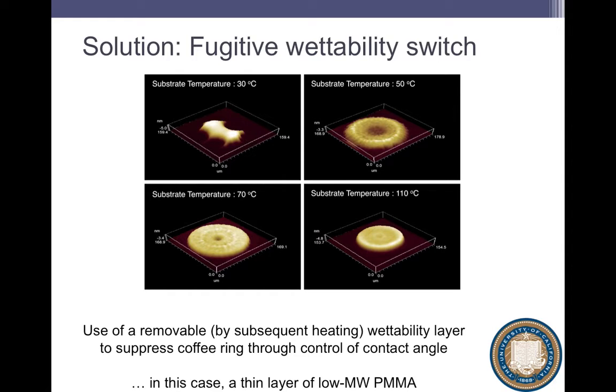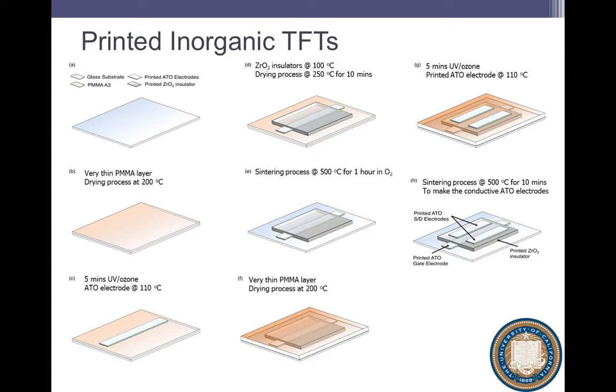So what we do is we put down, by print, a very thin layer of an organic, and then we hit it with UV ozone inline. And that micro-roughens the organic. And then when we print the sol gel, it forms a nice smooth shape. When we convert the sol gel afterwards at 400 C, it turns out the organic burns off and doesn't seem to impact performance. So take a glass substrate, print our gate.